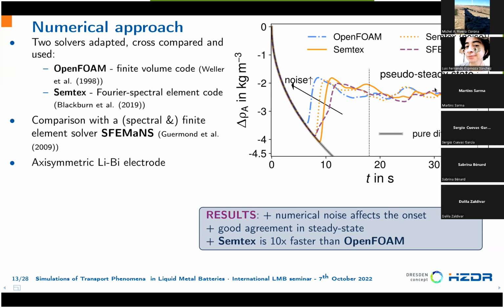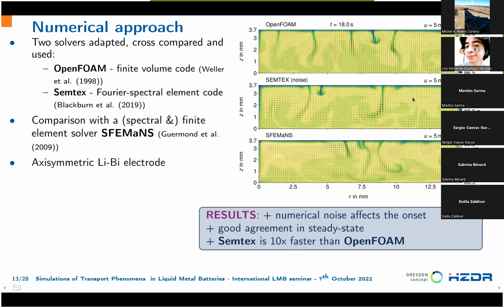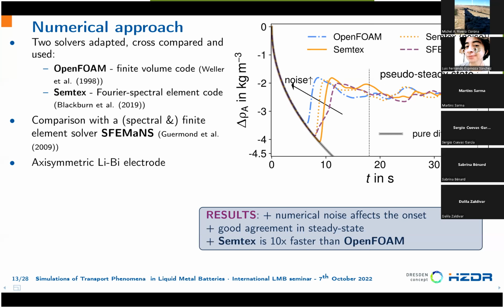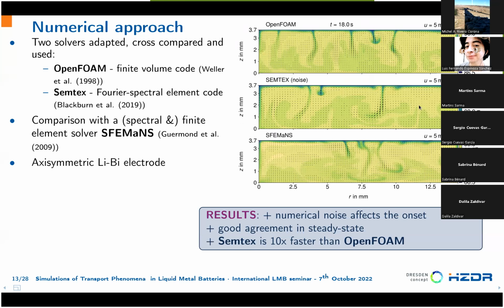Later, during the pseudo-steady state, the three solvers converge to a similar pseudo-steady state evolution. And if we compare now the concentration and the velocity distribution at the same time, we see that the structure size is similar across the three solvers. And yeah, the phenomena look quite similar. So this means that we have a good agreement between the three approaches. Of course, the effect of noise determines where the plume starts and the onset, as discussed.